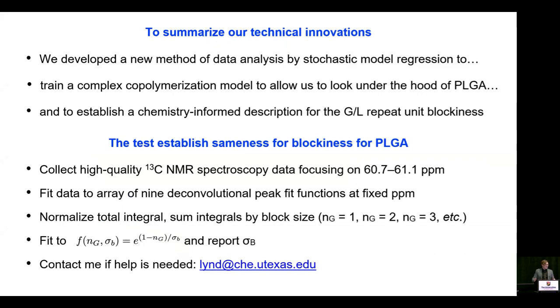So we developed a new method of data analysis by stochastic model regression that allowed us to train a complex copolymerization model that lets us look under the hood of PLGA and to establish a chemistry-informed description of the glycolide lactide repeat unit blockiness. And how you do this is collect high-quality carbon-13 NMR spectroscopy data, focusing on the region of the glycolide-centered methylene at around 61 ppm, fit data to an array of 9 deconvolutional fit functions at fixed ppm, and then normalize the integral, sum them by block size, and fit to that function and report sigma b.